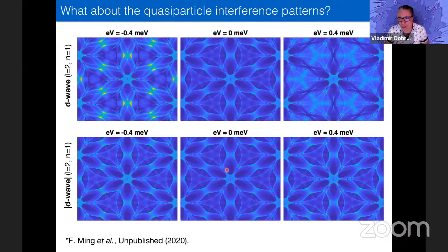So they made a big deal out of this. Apparently, this is seen in Seamus Davis's experiments where, near the Fermi energy, you see images which are very flat. And if you just do Bogoliubov-de Gennes without this quasiparticle normalization, then you really get a lot more inhomogeneity. What we found is that there's a very similar effect in the normal phase, and the same type of healing kicks in relatively close to the Mott transition. So it's a many-body effect.